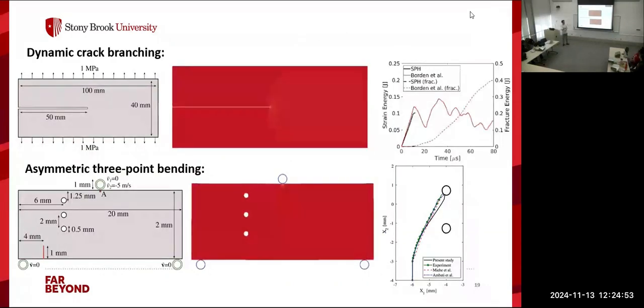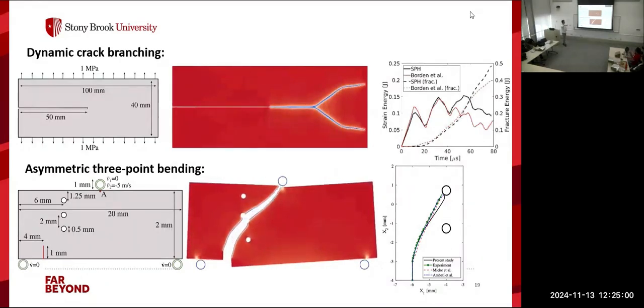We wanted to see if this fracture model is good enough to solve any fracture. Here, what you see is a very simple tensile case where the material is pulled from two parts and there is a pre-existing crack. Then it evolves into this and then branches into two. This is a very common benchmark that people use in fracture mechanics. And as you see, the results are in good agreement with the literature. Also, there is this one, which is also common, but with more complex geometry. Here we have random holes placed in the domain, and we have a pre-existing crack. When you apply a 3-point bending force, it cracks like this. And this is the comparison between experiments and other numerical methods, and you see how good the fracture surface is.